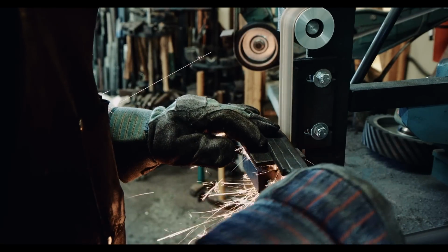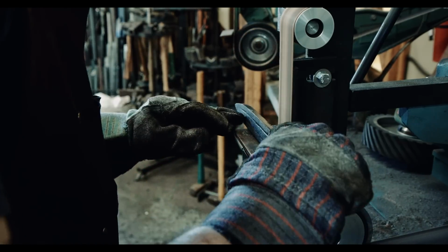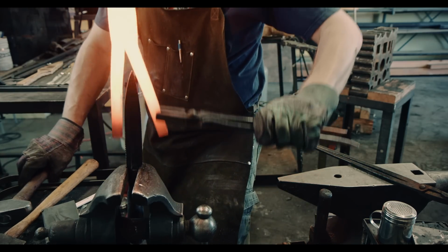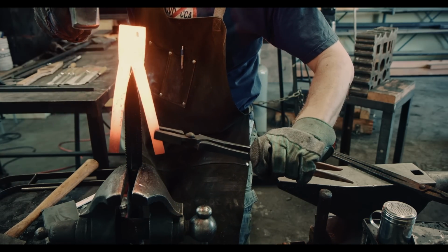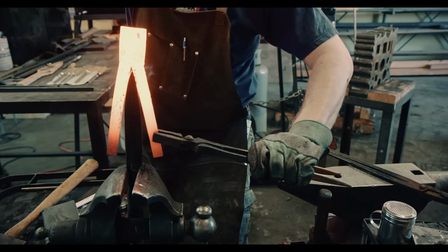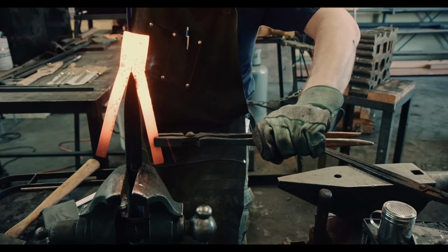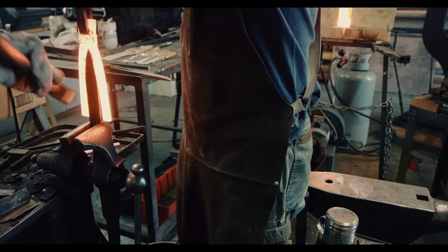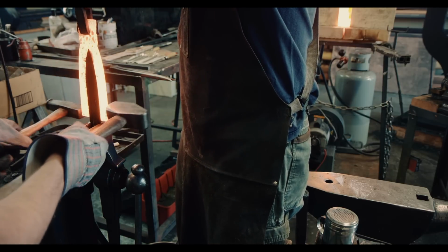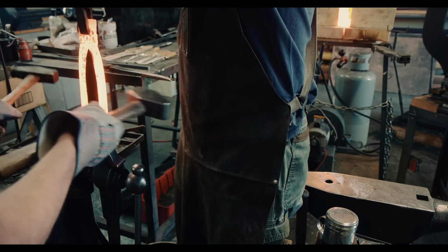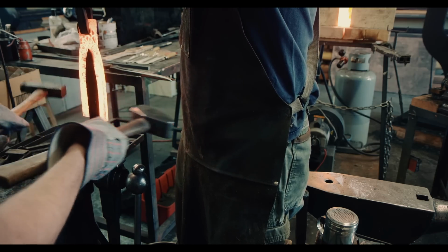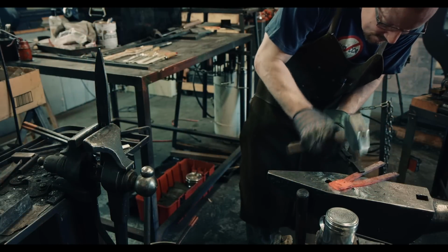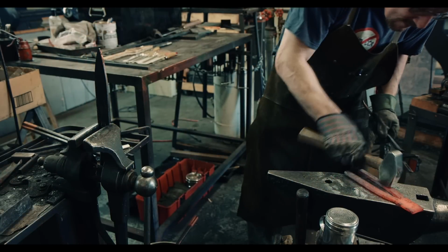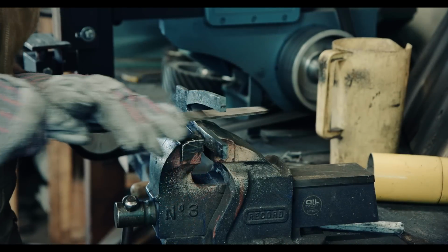When forge welding, it is also very important to have a good fit. Since I cannot aggressively forge the shape, closing up gaps will not be possible. As you can see here, the fit is not good at the moment and it takes a couple of iterations to get it right. Closing the gap at the top opens up the arms, closing up the arms creates more of a gap at the top. Since the adjustment was done at high temperatures, any newly formed scale needs to be removed again.